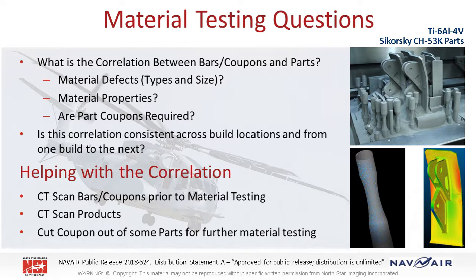Additionally, it needs to be understood if the correlation is consistent across build locations and from one build to the next. To help with that correlation, all the bars, the coupons, and the parts can be CT scanned prior to material testing. For example, you don't want to have material properties from a clean tensile bar represent a part that's filled with microporosity.